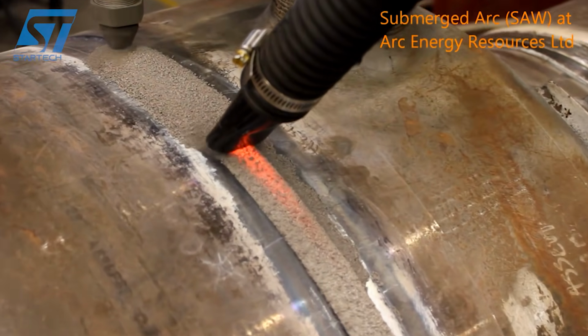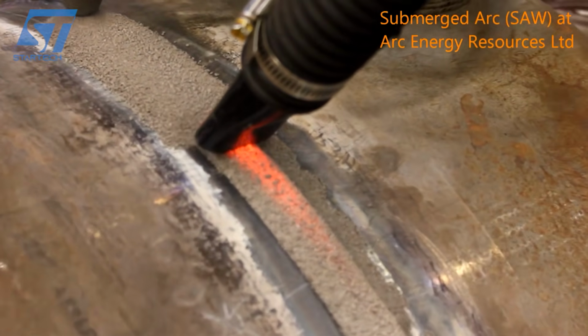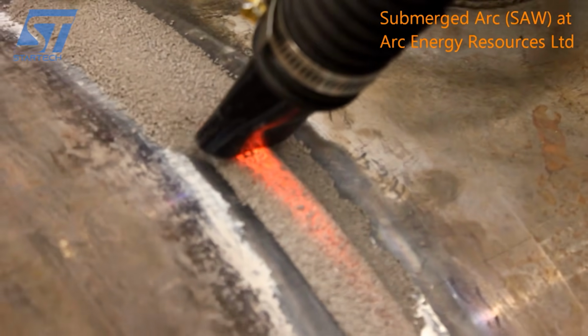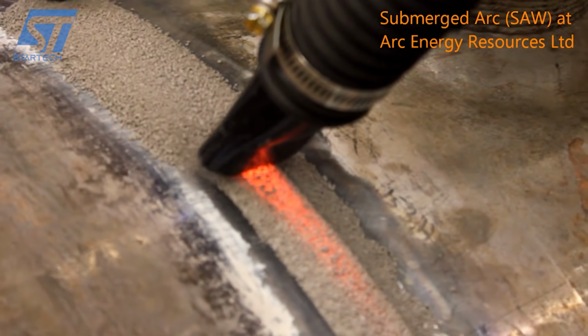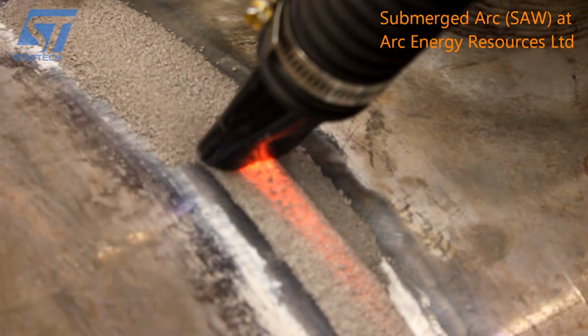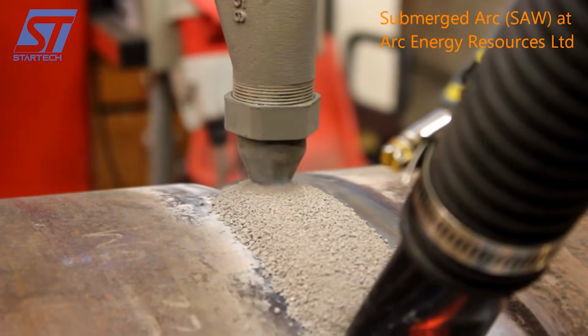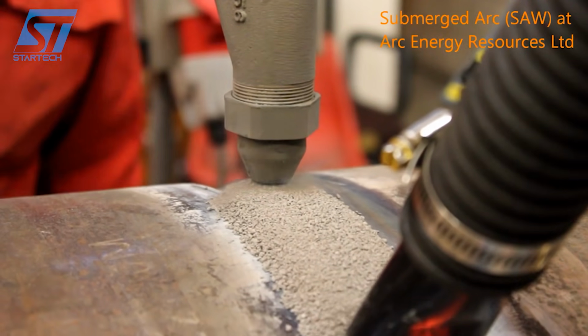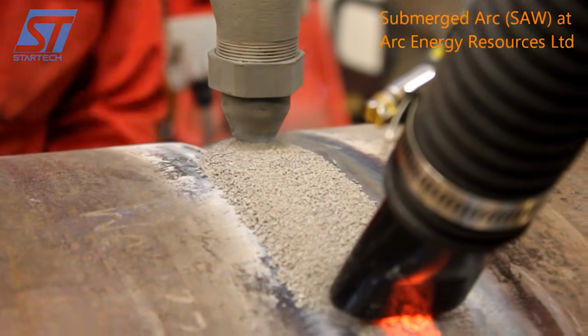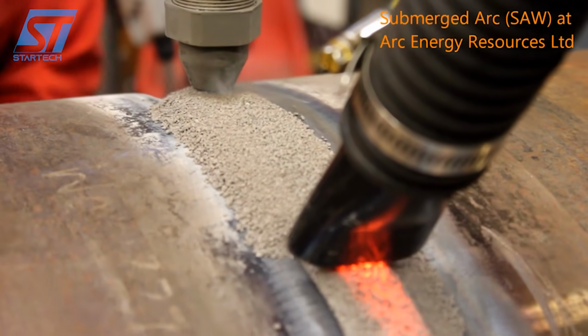The flux also serves as a chemical shield. It prevents oxygen and nitrogen in the surrounding air from contaminating the weld pool, two elements that would introduce porosity and brittleness into the finished weld. The result is an exceptionally clean, smooth weld bead with virtually no spatter and minimal fume generation.